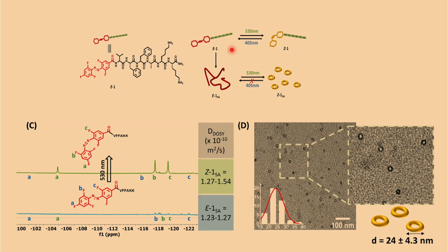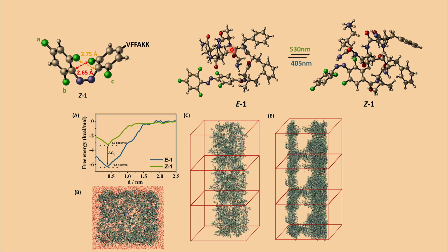That is what we are thinking, that maybe the adjacent fluorine is participating with the carbonyl. Some of these things we are now trying to validate with MD, and I will show you a very nice MD simulation data. As I was saying, this is coming very close, and you can see over here this is also coming very close to the carbonyl, which might indicate neighboring intermolecular participation, and we actually looked at it. In MD simulation of the E form, you see very nice fiber-like formation, this 1D growth of the fiber. Our collaborator has done this.